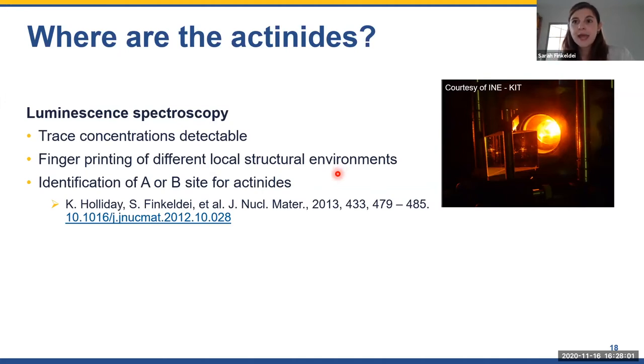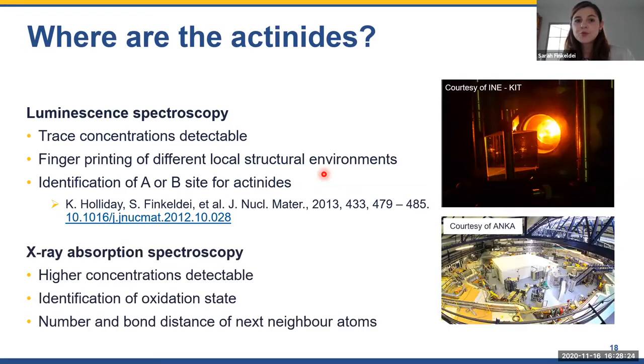So what we did is, because if you remember the structure slide I just showed you, the A and the B site of a pyrochlore have different environments, we could, with time-resolved laser fluorescence spectroscopy, determine that curium was structurally uptaken on the A site in a pyrochlore. And once we had performed these experiments with trace amounts of actinides, I moved towards more realistic waste forms where we want to have higher waste loadings, because obviously we don't just want to immobilize 10 ppm of a nuclide of interest that we want to store in a waste form, because then we would just create tons and tons of waste.